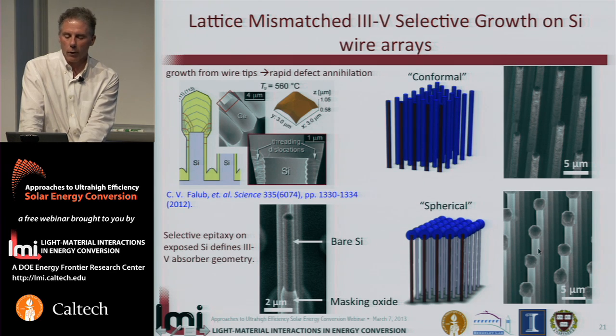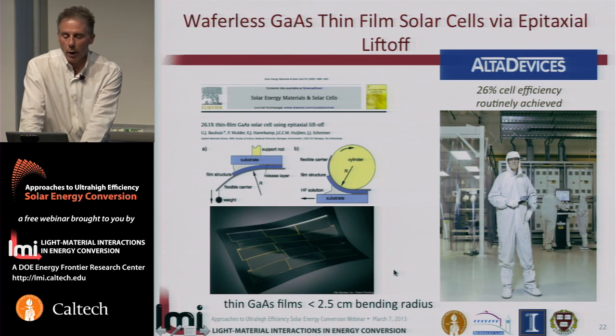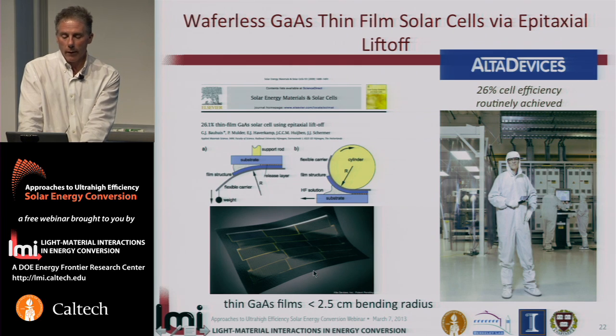And indeed, the other thing that's striking is that the photoabsorption and photocurrents achievable in this kind of structure are actually matched between the silicon and compound semiconductor layers. Ultimately, though, we want to work with the highest possible quality materials, and I know Eli will say a little bit more about this, and that involves use of single crystal materials, for example, of III-V compounds like gallium arsenide.